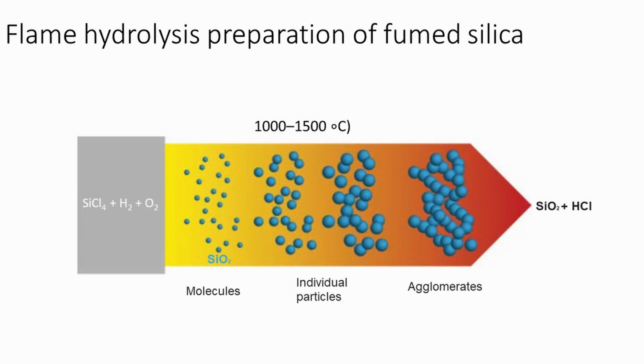A widely used preparation route for metal oxide nanoparticles is via a gas phase reaction, for which the product is often called fumed. The process involves reacting a metal oxide precursor at high temperature with water or oxygen, as illustrated in the figure. As a precursor, often a metal chloride is used, and the temperature typically varies from 1000 to 1500. Small clusters are formed which then aggregate into larger units, with the porosity of the material represented by the space between the primary particles. Flame hydrolysis is used on a large industrial scale to produce high surface area metal oxide powder with very high purity.